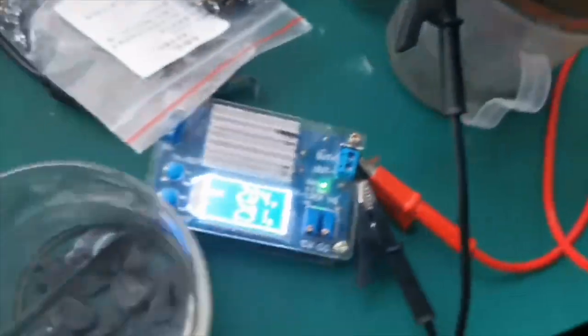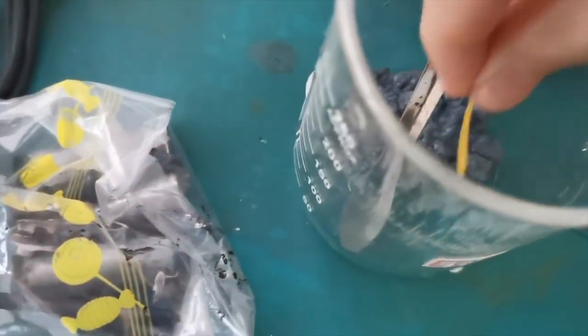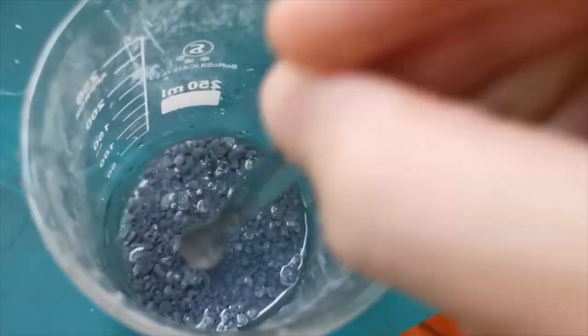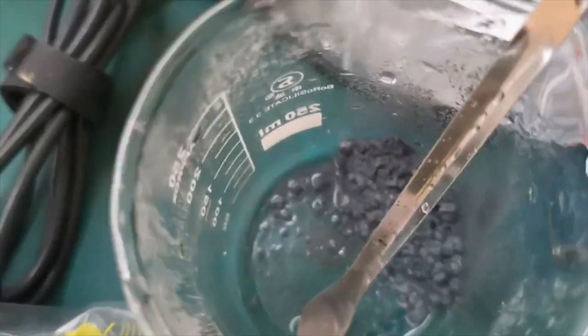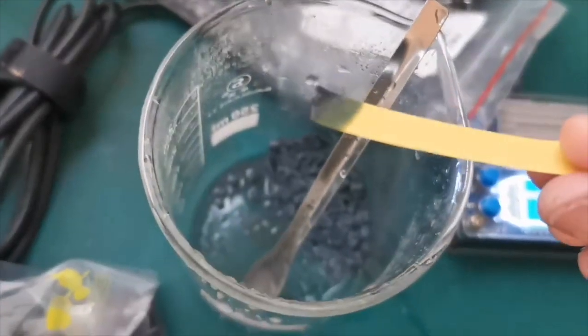The zinc in the beaker now looks like a gray black sponge and we are going to purify it. The water is decanted off and the pH tested to be strongly alkaline. The zinc is then washed three times with about 20 ml of water each time. After the final washing with water, the pH is tested again to be only slightly alkaline.